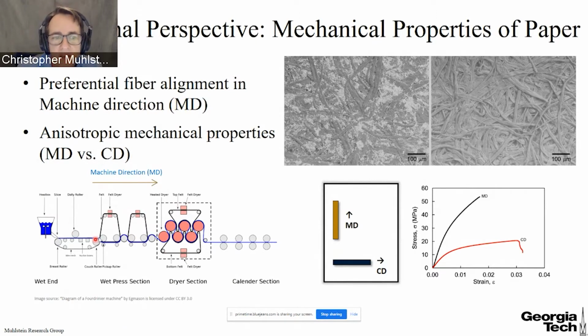The result of this is that as we push the paper through along what we'll call the machine direction, the fibers are going to tend to preferentially align. So when we look at this spaghetti network, this mess in the top right-hand corner of these two scanning electron micrographs, knowing where those fibers are in the local context hides from us the fact that they're biased in their orientation.